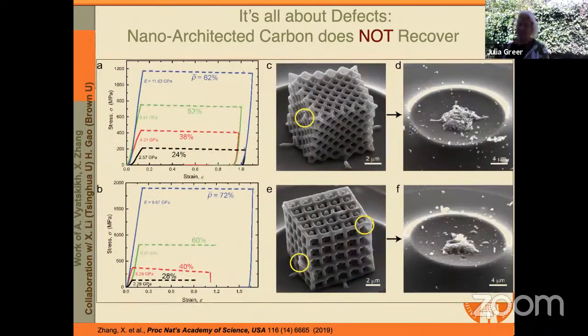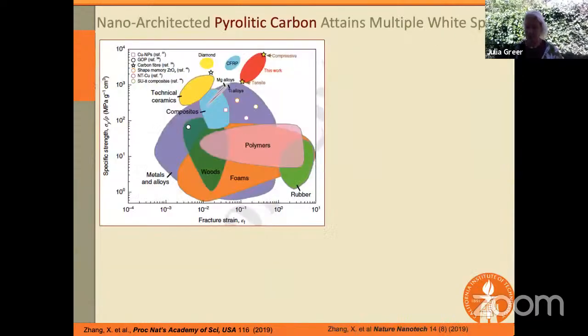All right, so now that we know that these nanoscale building blocks are able to behave like rubber, why don't we make these architectures out of them, right? Because then they should also spring like rubber. And what we learned is that in the case of carbon, non-hollow tubes, we always destroy the nanolattices. So even though the behavior of each individual building block is recoverable, when you start constructing a nano-architected material out of it, it shatters every single time and fails brittly. And the reason for that is, of course, the presence of the defects and the presence of these junctions. And so this is what I would like to highlight here, which is the importance of defects and their role in the deformation of the material.